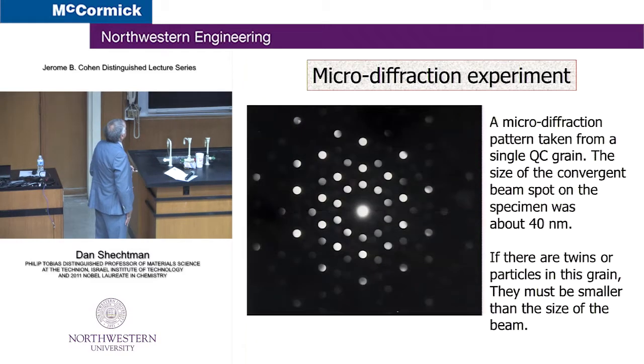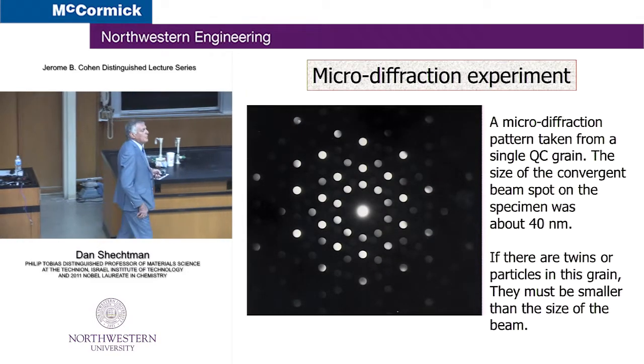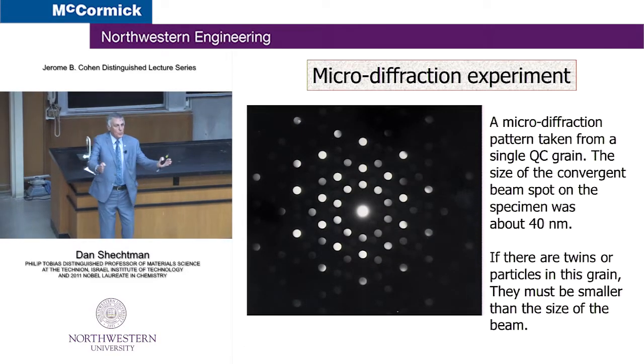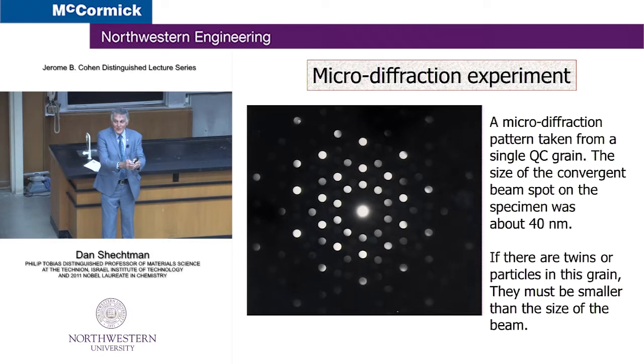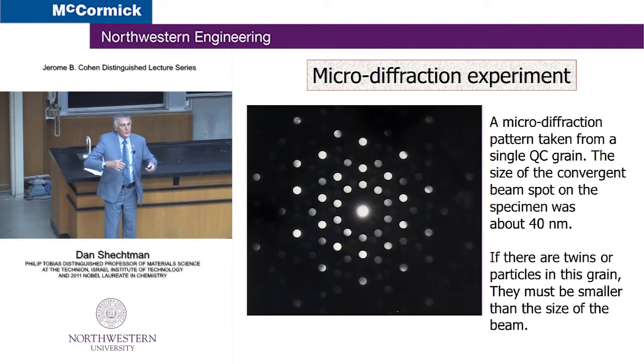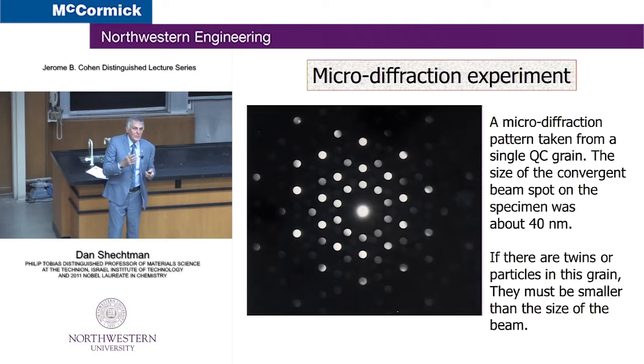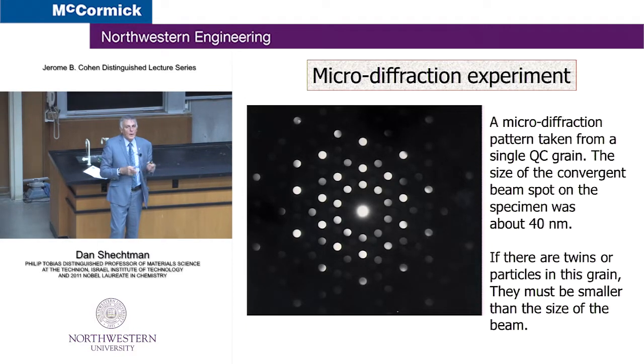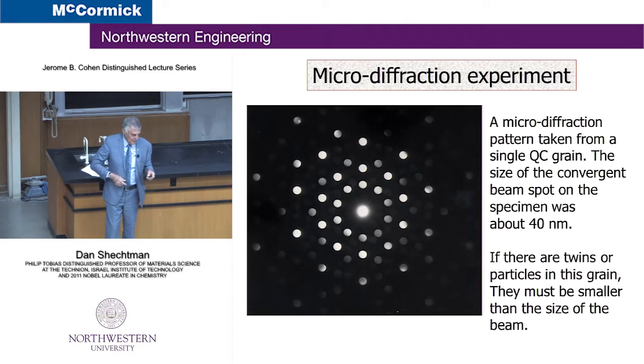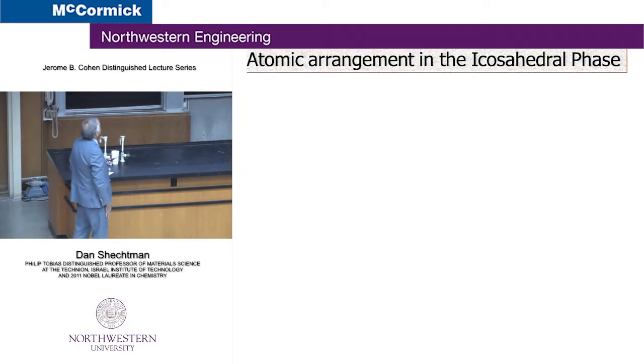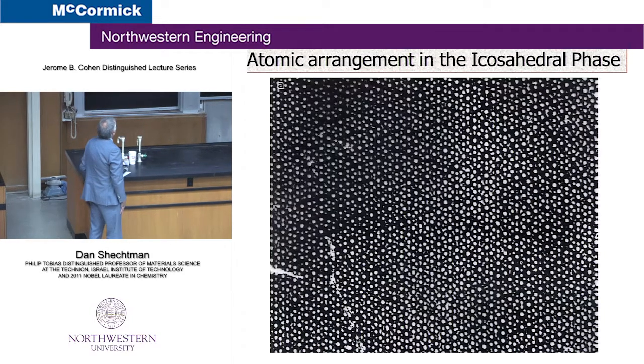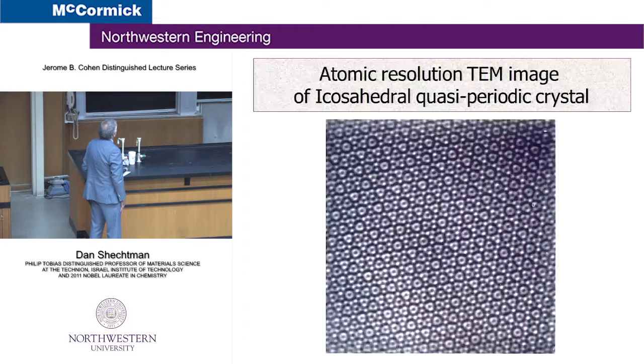I did also micro-diffraction called CBED, convergent beam electron diffraction. What you do there is you converge your beam in an electron microscope into a very small spot, and you take a diffraction pattern from that spot only. And if there are twins, then the twins must be smaller than that spot. And the size of that spot on that microscope was 400 angstrom, 40 nanometers. If there were twins there, they were smaller than 40 nanometers. Very unlikely. Okay, we'll also skip this experiment, although it's quite interesting.